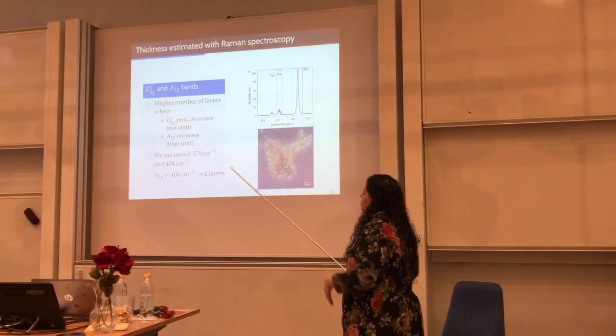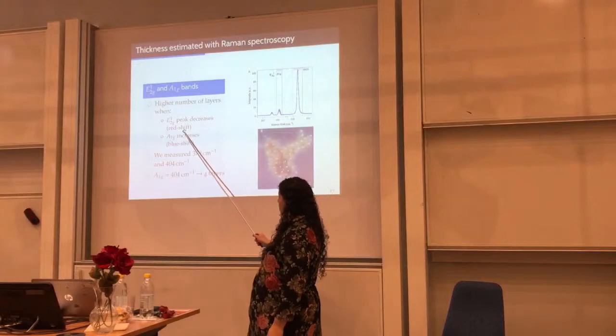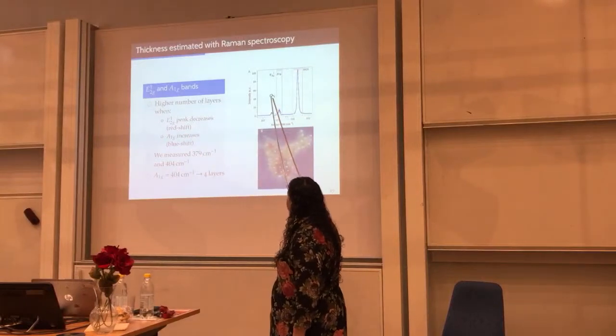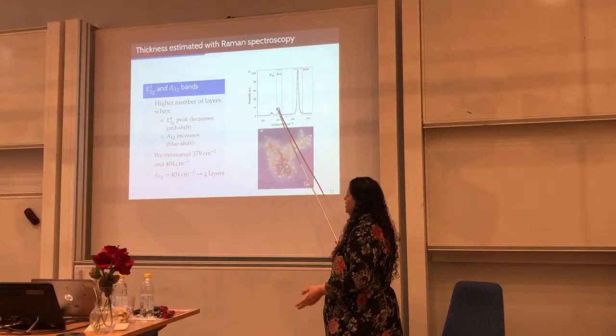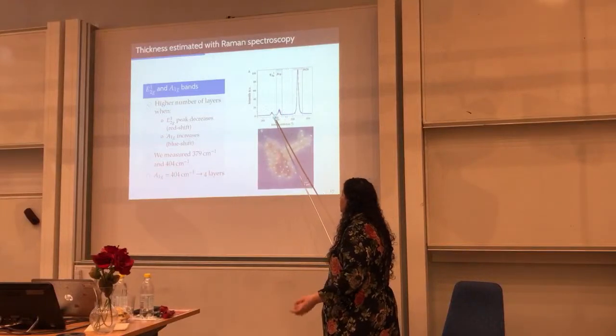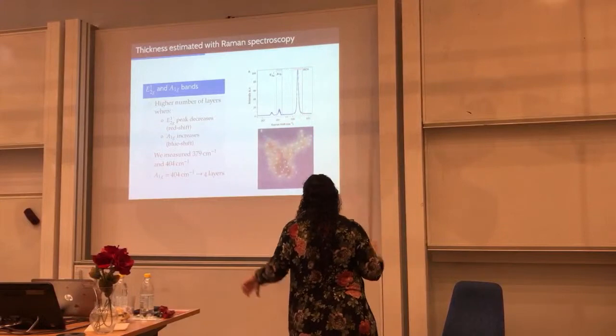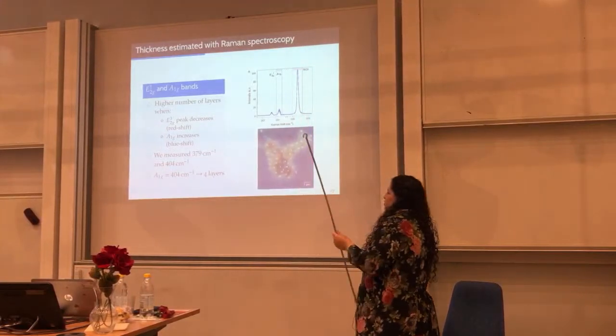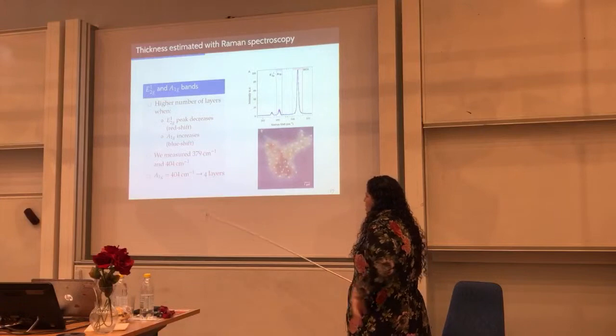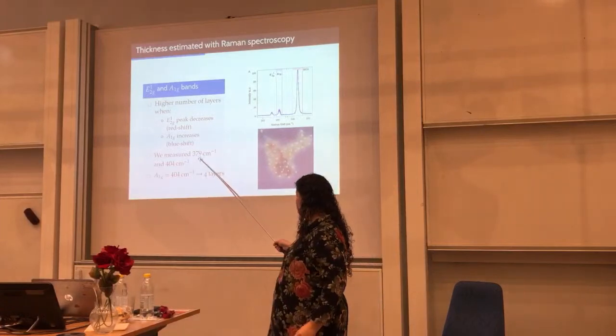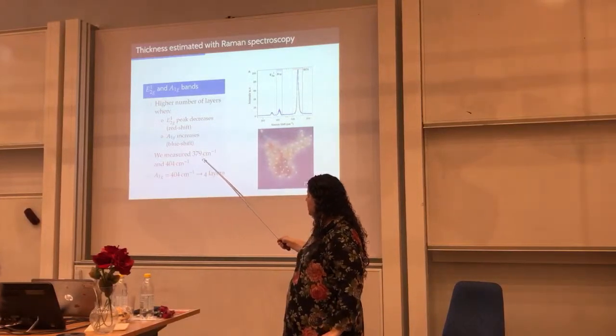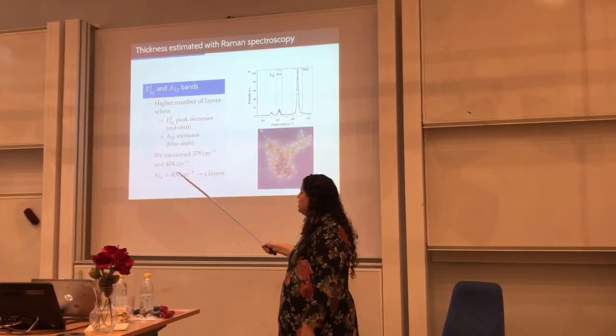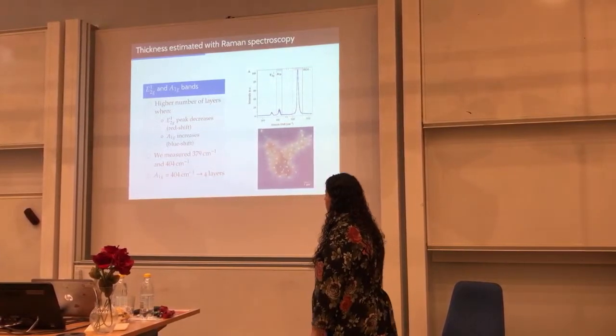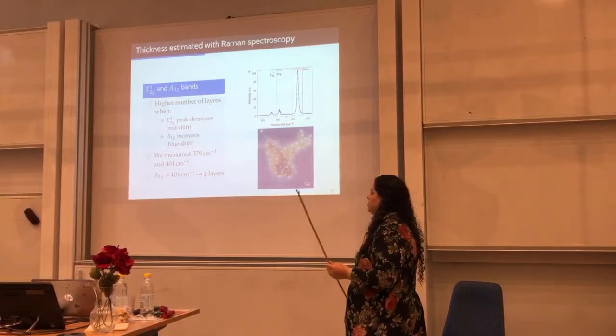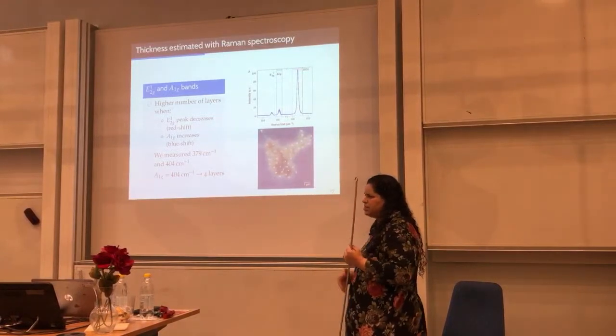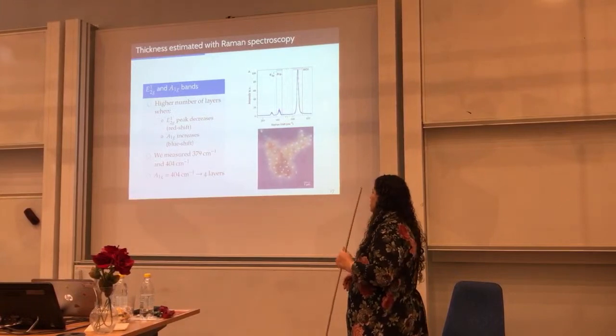And once you follow the position of these bands, you can tell how many layers of the material you have. So basically, you will look at whether this band here is moving towards a red shift, and this one is moving towards a blue shift, so that if they are separating, you have thicker particles. So we measured these bands at 379 per centimeter and 404 per centimeter frequency. And according to the literature, we would have about four layers, which is okay for liquid phase exfoliation.